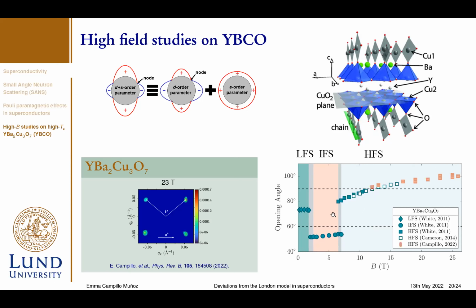However, we are happy to say that we were able to measure the vortex lattice and the form factor of YBCO up to 25.9 Tesla. This is the first time that the vortex lattice has been seen with neutrons up to that field. It's also important because we obtained this data using time-of-flight experiments and not monochromatic instruments.